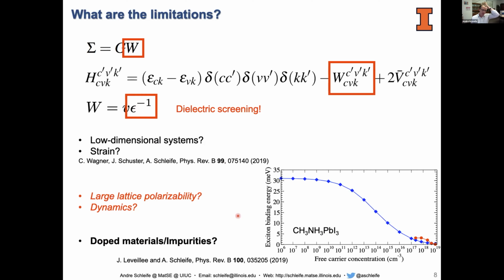And so we did this a couple of years ago for zinc oxide. Here I want to show you some data briefly for methylammonium lead iodide, where we actually calculated the exciton binding energy using this framework and accounting for different electron doping concentrations. So that's the x-axis here on the plot, right? The doping concentration, and then we calculate exciton binding energies in this material, simply because, for photovoltaics, the exciton binding energy is relevant if you're thinking about separating the electron and the hole after you created it. Then too high binding energies are not so good, and too low binding energies may be preferred. And so the question is, what is the exciton binding energy?